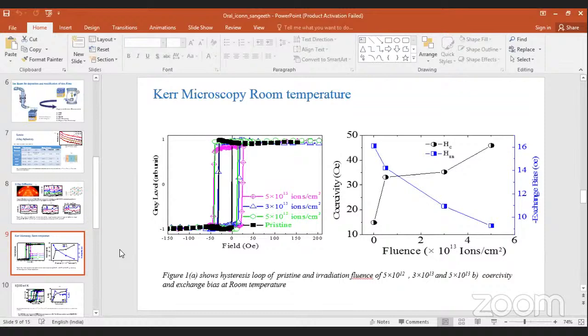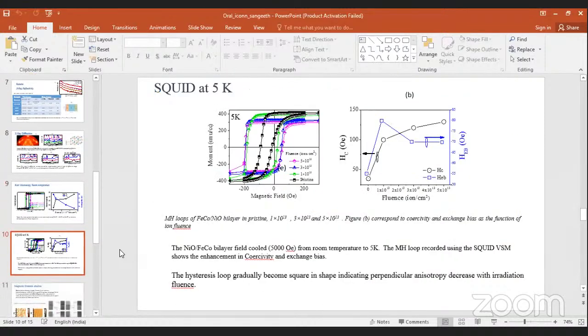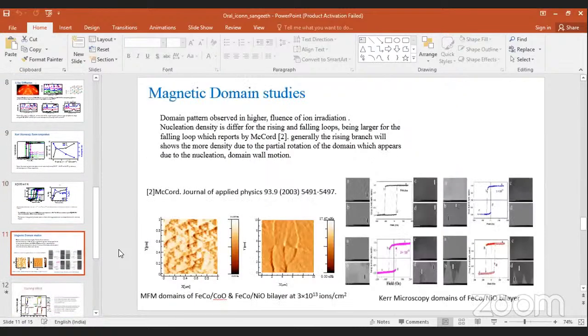But to understand more about the exchange bias, we again field cooled the system from room temperature to low temperature, that's 5 Kelvin. Then we can see that the exchange bias and the coercivity are both enhanced. This means that the frozen spins present at the interface may contribute to the enhancement of the exchange bias.